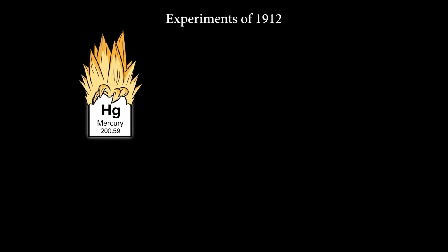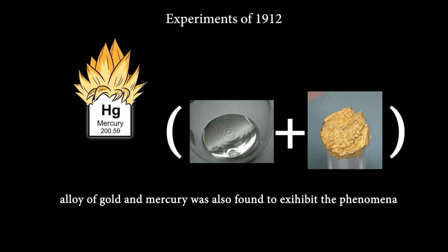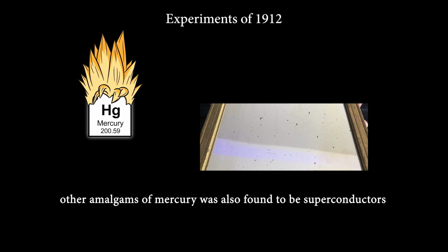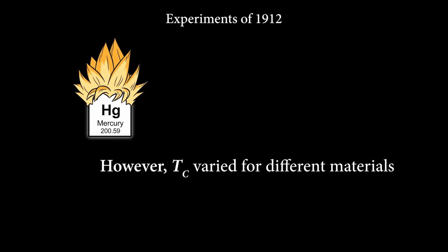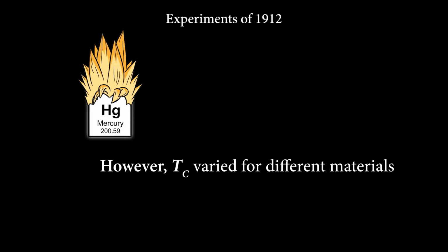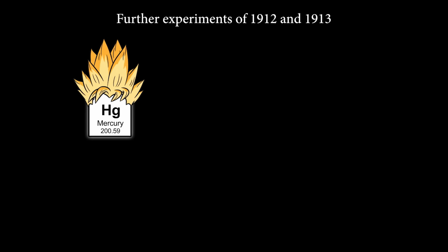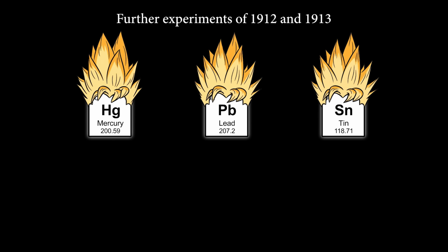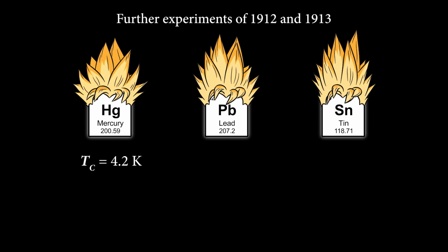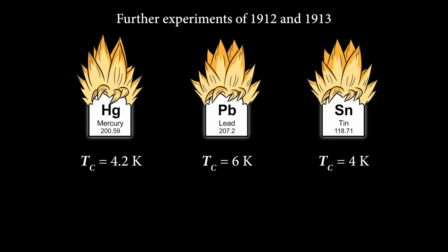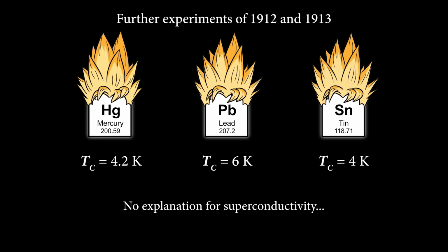In the experiments of 1912, it was found that superconductivity wasn't a phenomenon which occurred in ultrapure mercury only. The resistance of the alloy of mercury and gold disappeared in the same way as with ultrapure mercury. Even for mercury amalgams that are used for backing of mirrors, the resistance would be found zero at liquid helium temperatures. However, the exact critical temperature for the transition varied. In a lot of experiments in 1912 and 1913, the Leiden team would discover lead and tin to also be superconductors. The transition temperatures of these would be around 6 Kelvin and 4 Kelvin respectively. There was no theoretical explanation for all these experimental results.